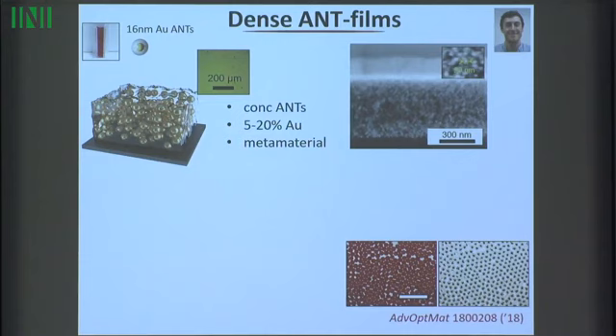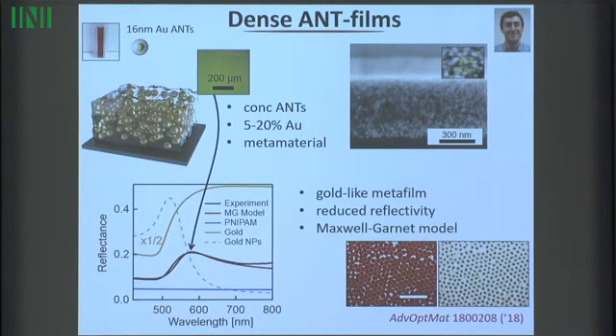It's what we would call a metamaterial. So I should be able to get some average property of this system. One interesting thing that I can do is just look at the color of the system, and already I have a problem in trying to go between gold, which has a reflection spectrum that looks something like this, and the polymer we're using, which has a very flat reflection spectrum like that. And if I try and make some sort of model about what the reflection spectrum looks like, I start to get into problems because of these very strong couplings, because these particles are very close to each other. So a mean field model doesn't really work in this system. But because it's disordered, I can't use all the typical formulation that we have for, say, periodic materials. So I'm faced with doing extremely difficult simulations that have millions and millions of these spheres in, and they're interacting very strongly to each other.